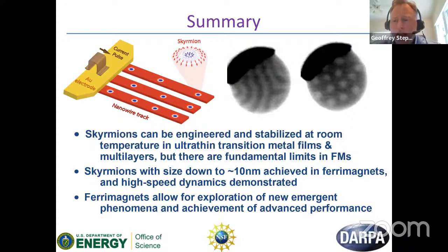So that I agree. It is always a difficult problem for driving either domain walls or skyrmions. And the current densities that are required to do that reliably remain very large. And they remain very large despite a number of years of work on the materials. And the other important thing that goes hand in hand with that is that the threshold currents are typically related to extrinsic defects. And therefore there's stochasticity, which would also be a killer for a racetrack memory in which you have to operate it 10 billion times and not lose a bit.